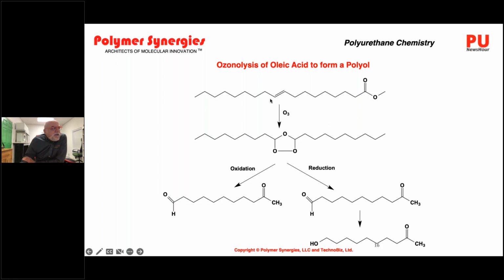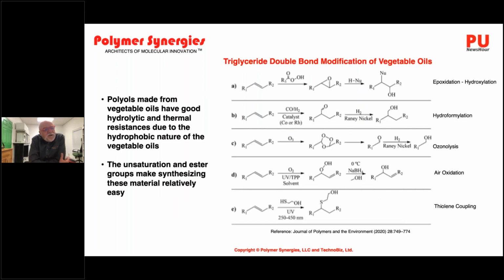And in ozonolysis, we use ozone to form a ring structure off of the unsaturation in the fatty acid. And then it either goes through an oxidation or reduction to get down to our polyol species. But that's not the only method of doing it. Polyols from vegetable oils can be manufactured via epoxidation, hydroformylation, ozonolysis, as I talked about, air oxidation, and thiol-ene coupling. So there are a variety of different ways to get at polyols from these vegetable oils.